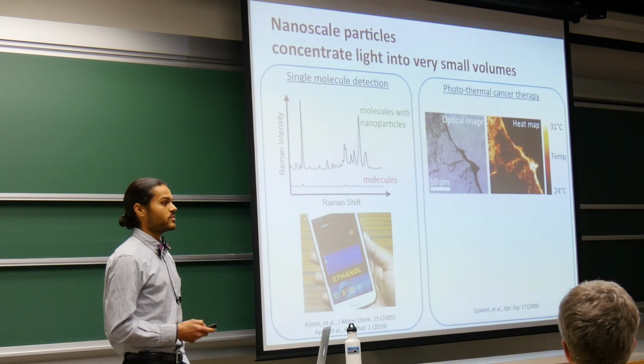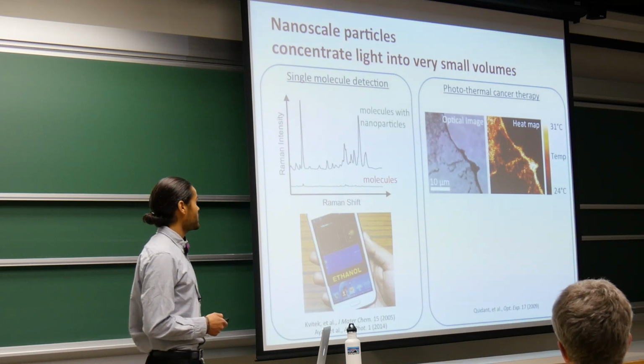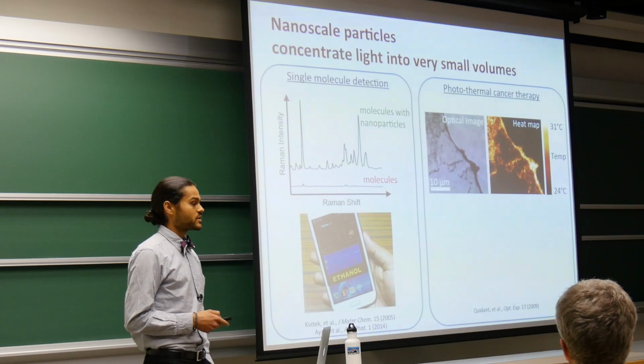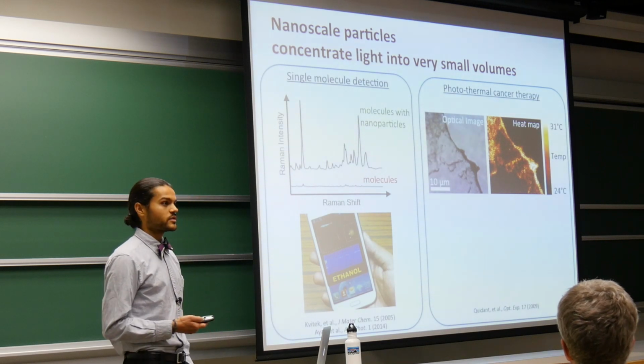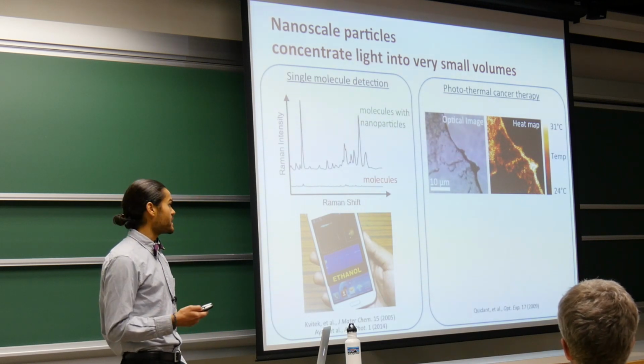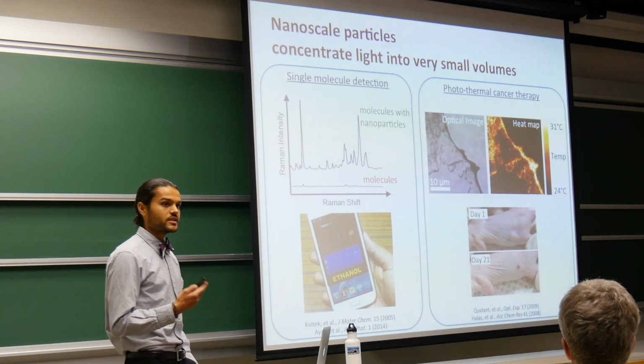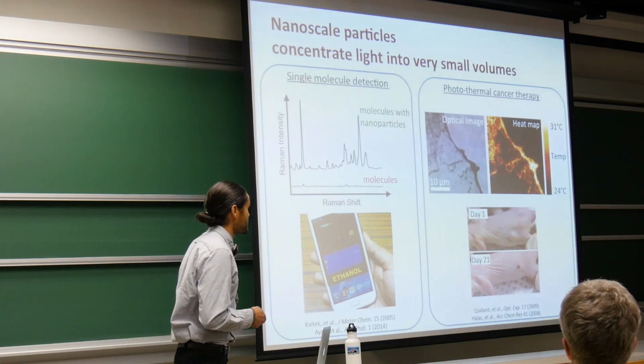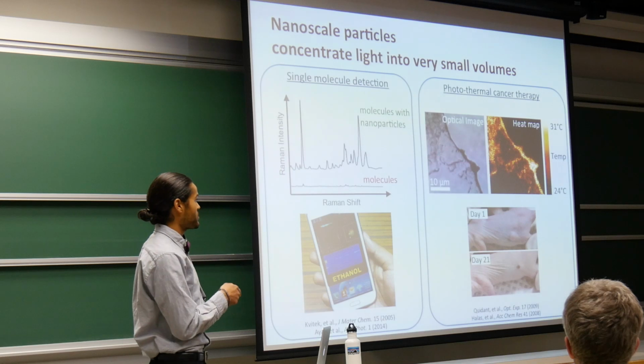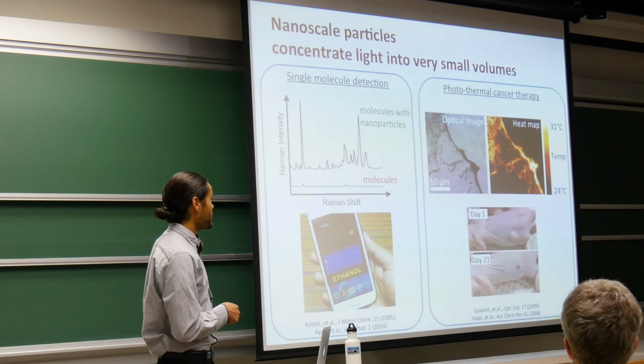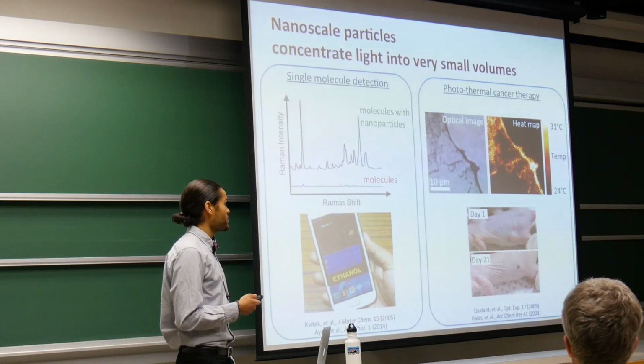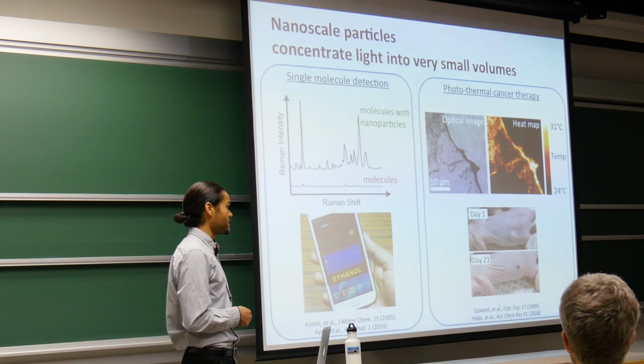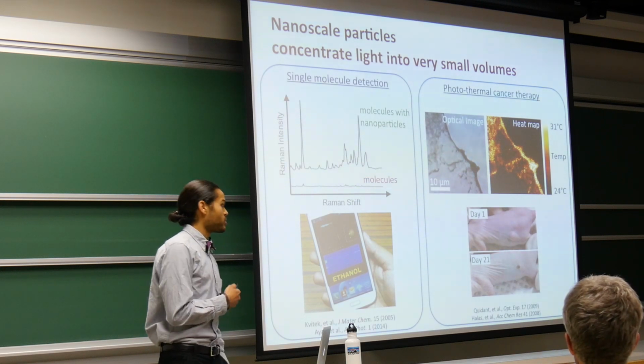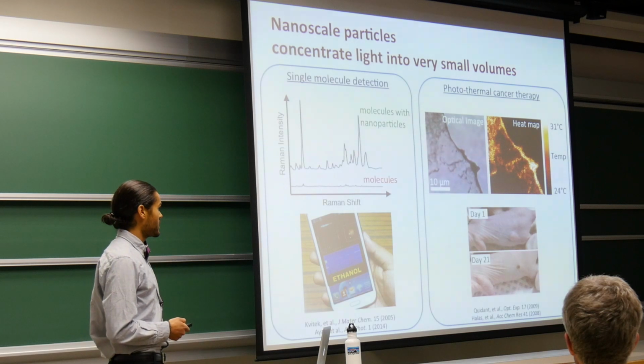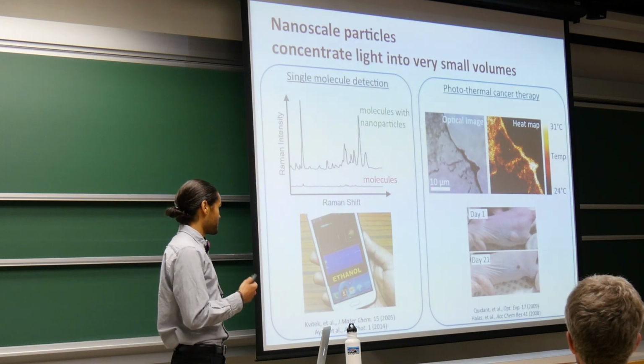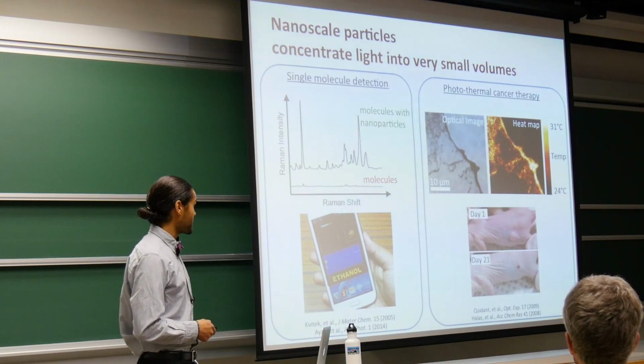Most of you are aware that biological cells, including our own, are very sensitive to their local temperature. So it turns out that if we put these nanoparticles inside of a tumor and irradiate them with light, we can actually kill off cancer cells. So here is a pretty disgusting looking mouse where they put nanoparticles into the tumor, illuminated it with light, and after 21 days, the tumor was essentially completely eliminated. And this process is actually currently being fast-tracked for human clinical trials.